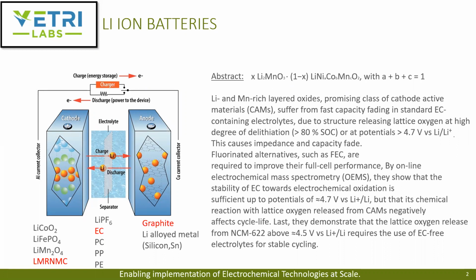They have studied fluorinated alternatives with fluorinated ethylene carbonate, and it seems to address and mitigate the mechanism associated with the lattice oxygen reaction with electrolyte.